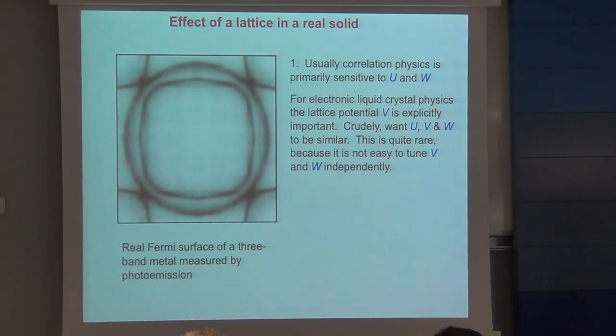But of course, if the lattice potential is extremely strong and it's binding your electrons very strongly to the symmetries of the lattice, it becomes energetically unfavorable to undergo a transition like a Pomeranchuk distortion, where the conduction electrons try to adopt a lower symmetry than the symmetry of the host lattice. And the key problem that you face is that we're used to the idea that we know tricks of how we change the U to W ratio in solids, but it's actually very difficult to change the bandwidth, the kinetic energy, without changing the potential energy, the lattice energy.